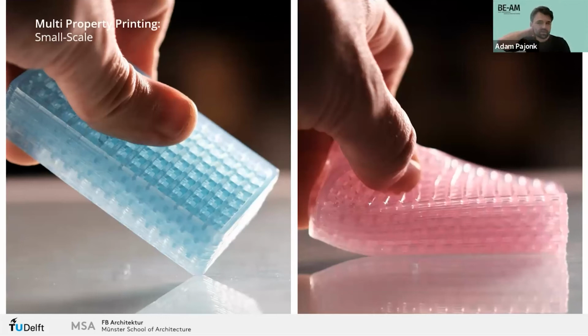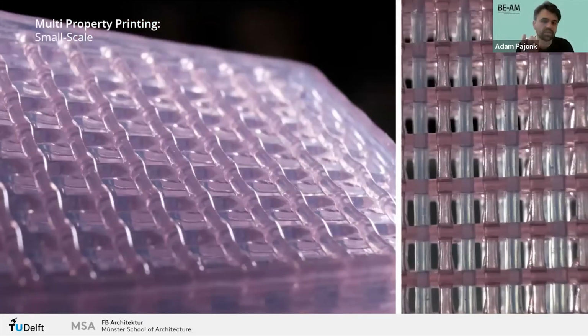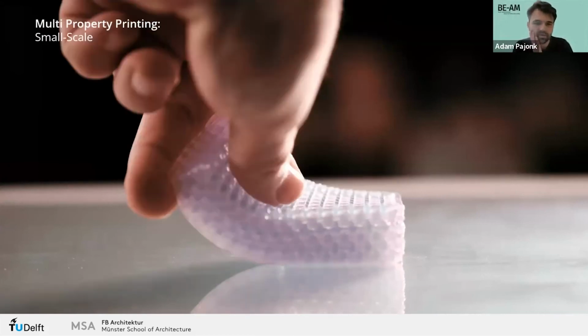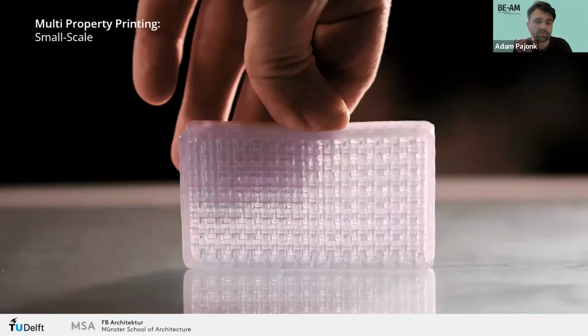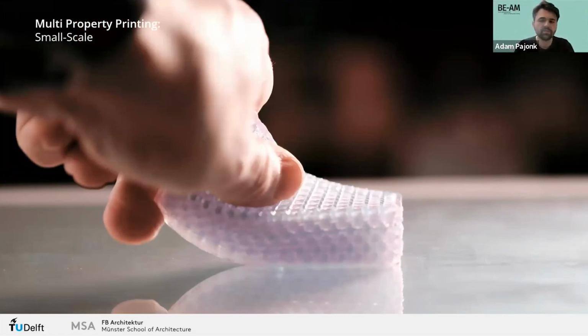And now with these parameters, we started to create the boundaries of the structure, with the maximum of rigidity on the left side with the hard compound, and on the right side the maximum of ductility with the soft compound. With these extremes in mind, we wondered what is in between, and we looked at possibilities to define the structure in order to achieve something which is neither completely stiff nor completely flexible. So we started to pick individual lines within this structure and assign different material properties to these, which ultimately leads to a structure that keeps a lot of flexibility, while also restricting the movement along the blue rods of the structure.